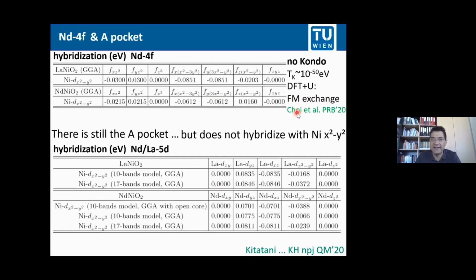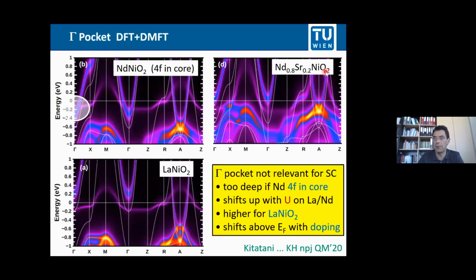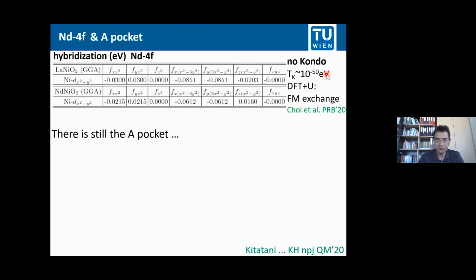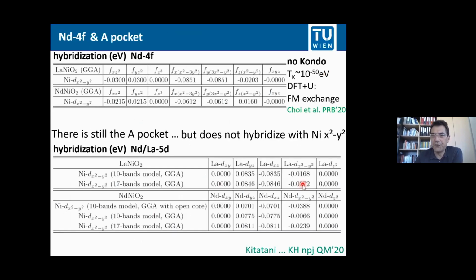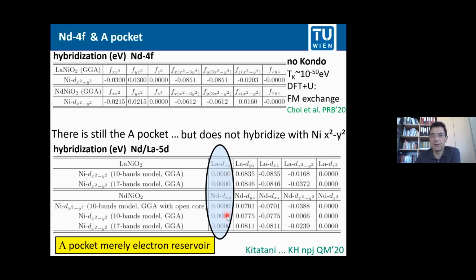The A pocket stays there. As you maybe also see here, also for the doped compound, the A pocket is still there. But by symmetry, the hybridization of the A pocket with the other orbital that is in the game, the nickel x squared minus y squared orbital, is 0. That means they don't talk to each other. The A pocket, except for maybe some residual Coulomb interaction, is just an electron reservoir, a passive bystander. As I will show you on the next slide, about 50% of the holes go into the A pocket and 50% go into the x squared minus y squared orbital.